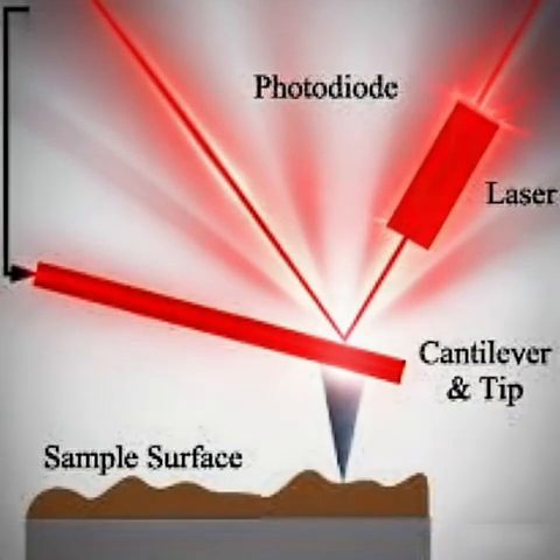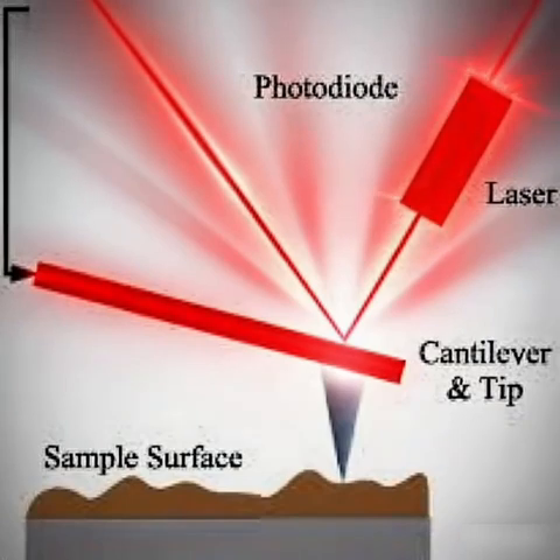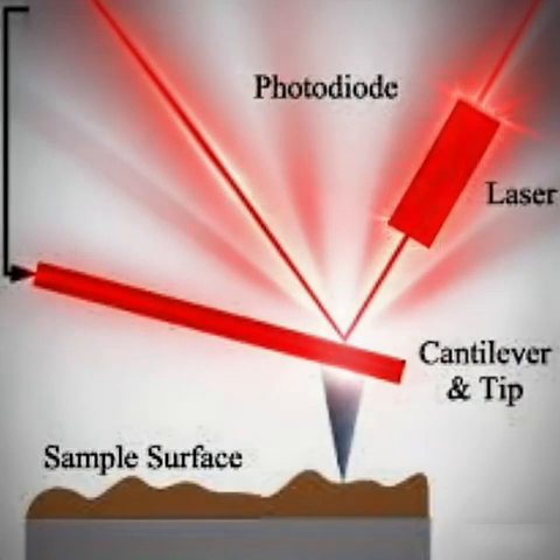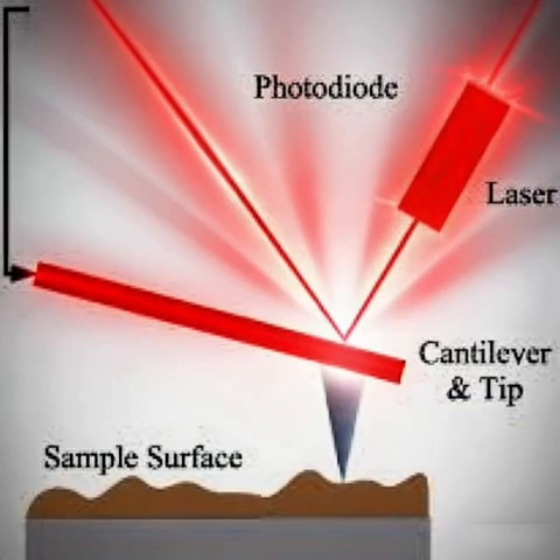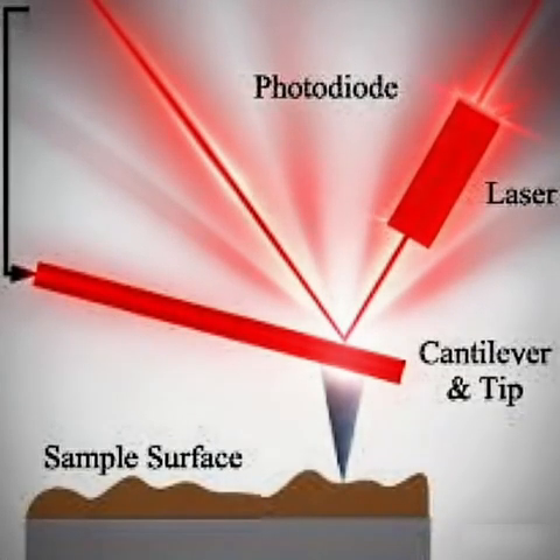And AFM methods are incredibly effective at finding this HCE damage. For instance, CAFM, the conductive mode, can detect those local conductivity changes. It shows engineers where leakage or current spreading is happening because of these hot carriers. Meanwhile, KPFM, the Kelvin probe mode, can analyze surface potential changes. That helps find the precise location of trapped charges, the evidence left behind by the hot carriers. It lets us pinpoint the exact damage regions. So if HCE is like this slow burn degrading the chip, AFM gives you the exact coordinates of that fire.